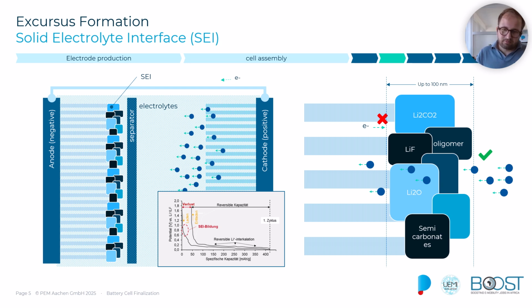An interesting fact, in the 1970s and 80s, a lot of batteries were built until the SEI was discovered. It was a big breakthrough. So researchers found that specific electrolytes would form a stable SEI on the anode side, which allows then a rechargeable cycling. And without it, a lot of early lithium metal batteries kept falling apart because they did not have this SEI layer and could allow only for a few cycles, reacting until everything was consumed ultimately. So this is, I think, a good example how a controlled imperfection, so this layer, actually makes things better.